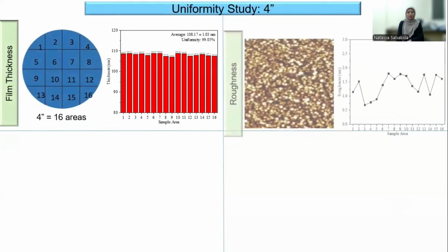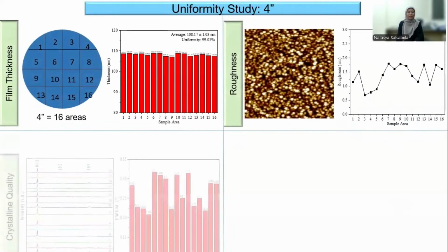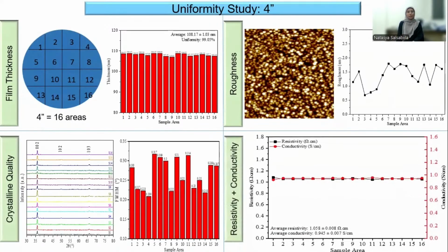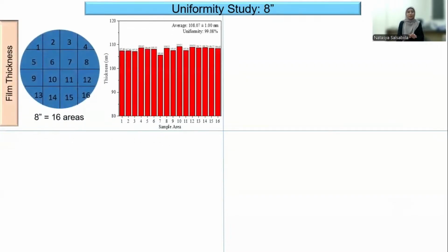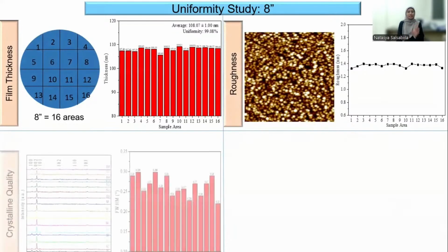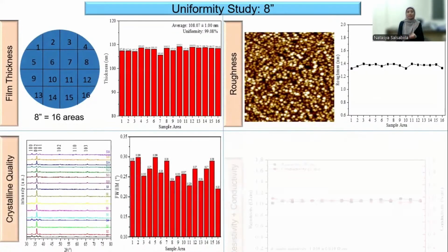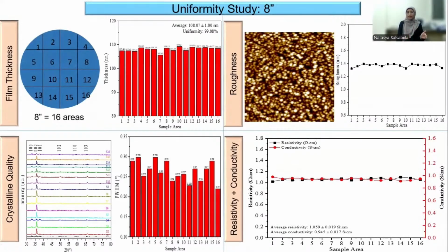Okay, we tried to make a larger area, which is a 4-inch wafer. This result also shows that the properties of the AlN film remain consistent, but small fluctuations start to appear. The final observations, of course, on the 8-inch wafer. This shows that the properties are still consistent, but some area on the edge of the wafer has a lower quality compared to the center area. But we can still use more than 85% of the wafer for the next device fabrication.